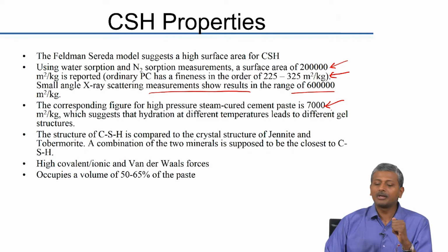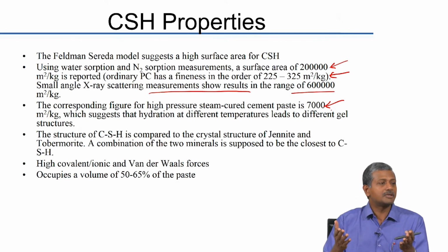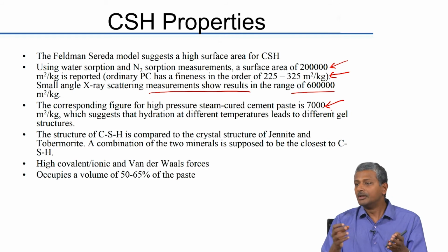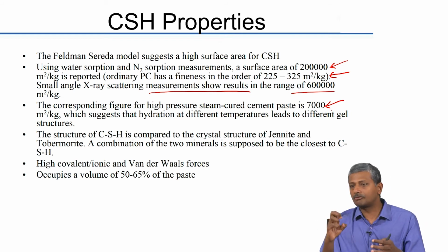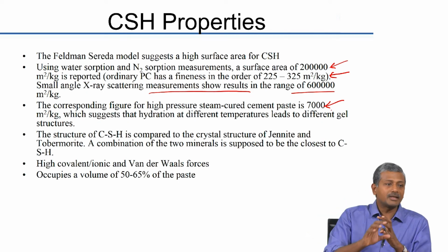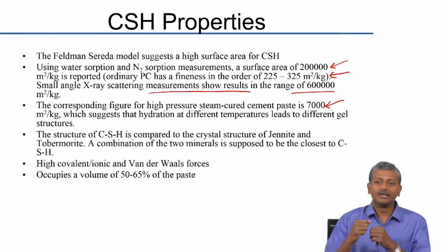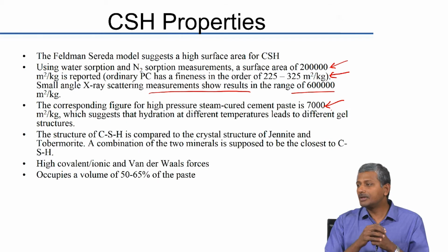And that is happening primarily because you are creating more coarse porosity in the system. Why does it happen? You can imagine it in the early fresh cement paste system, when you increase the temperature you are rapidly causing dissolution from the surface of the particles. So in other words you are forming this hydrated barrier structure much faster, and you do not give a chance for complete hydration to take place inside in the early stages. So this coarse porosity in the outer CSH is greater in heat curing.